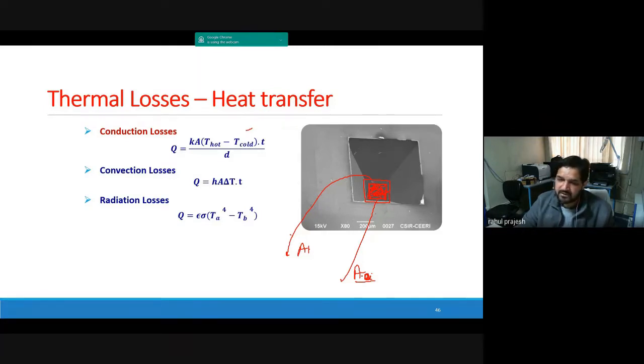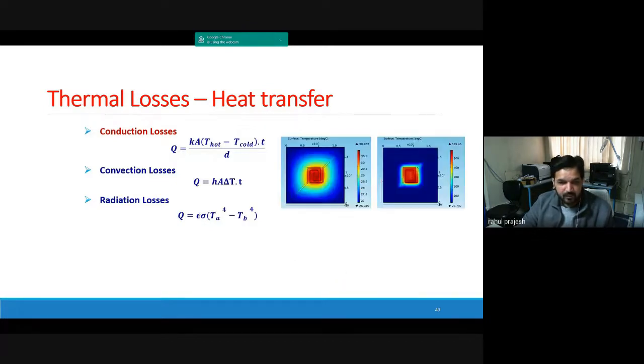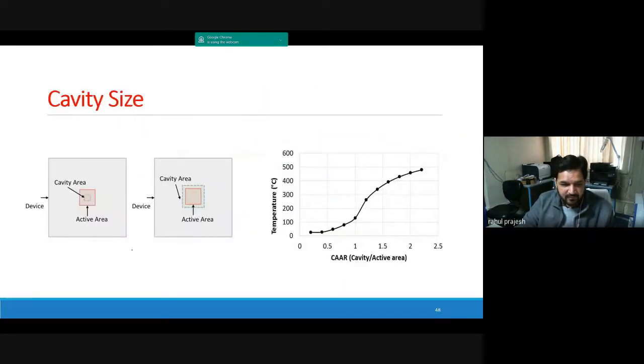But in most cases, it should be greater than the active area, because you'll have less thermal mass and you will have better efficiency. You can also optimize this with simulation. I have done some simulation regarding this, and it says somewhere around 1.5. So the cavity area is larger than the active area, at 1.5 times the active area. In this particular case, it could be more than that, but in most cases it gets saturated. So this range of 1.5 to 2 is what you should keep for a better design.